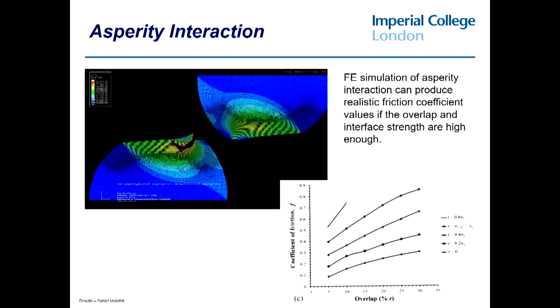Daniel did some very nice work at different overlaps and was able to generate estimates of the coefficient of friction. And you get some pretty reasonable answers, actually. But, of course, the trouble is we don't have the computational power to do this for realistic surfaces.